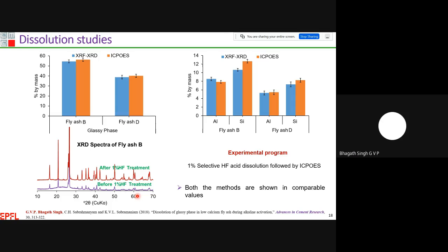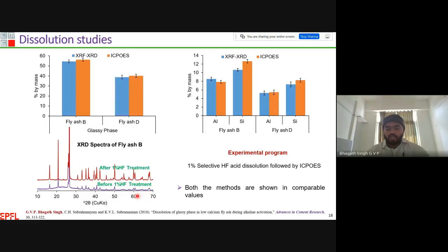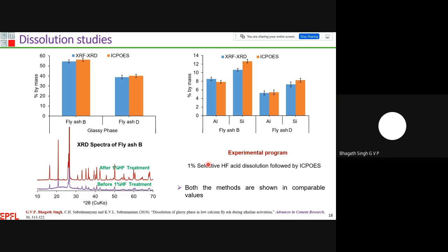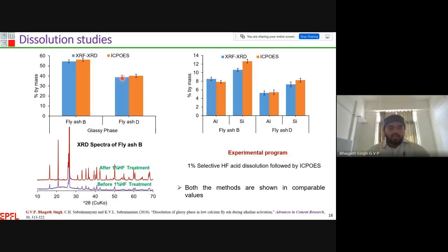I have observed those values also, but I'm not presenting them here. And I tried to compare this existing methodology with the XRF XRD technique with different fly ashes. One has about 50% total glass, another fly ash about 40%. And both methodologies fairly match, with very little difference. But I would not prefer the HF acid dissolution because it's a very harsh treatment and we have to wait much longer to achieve the result.